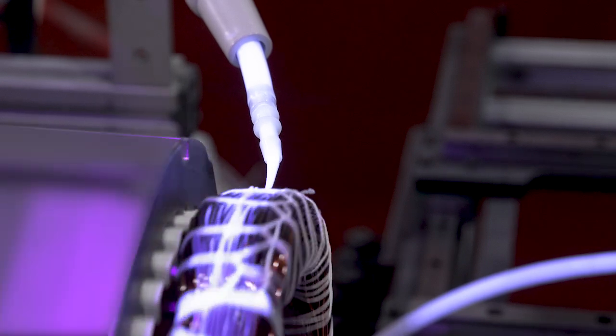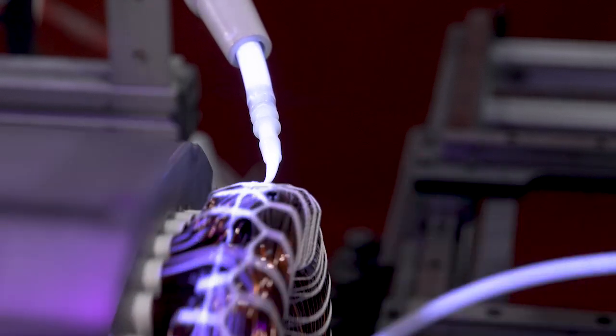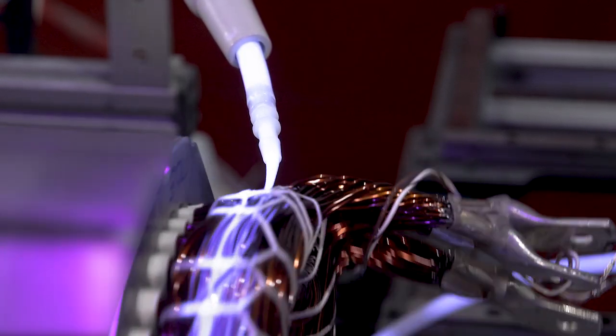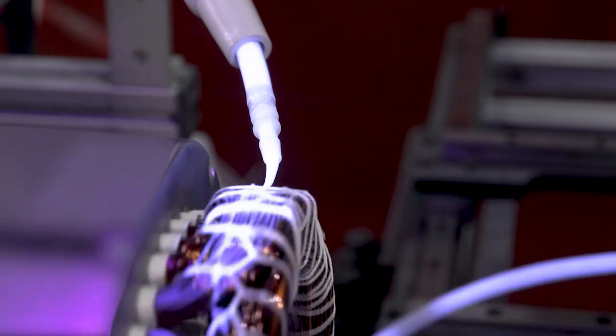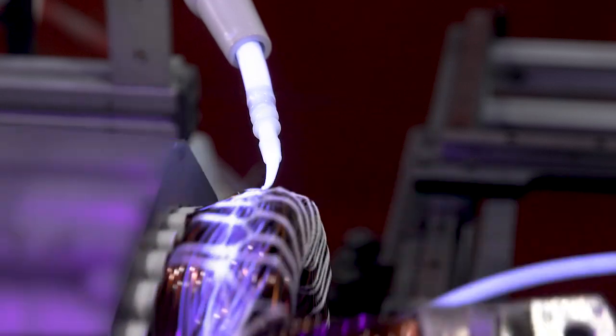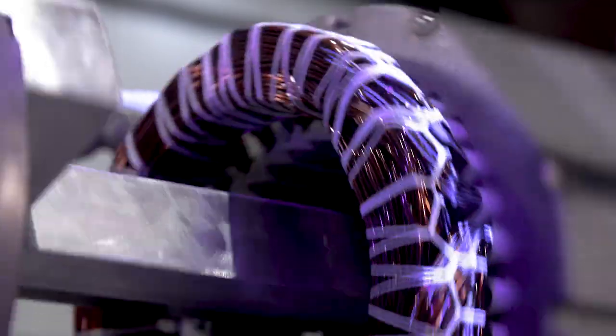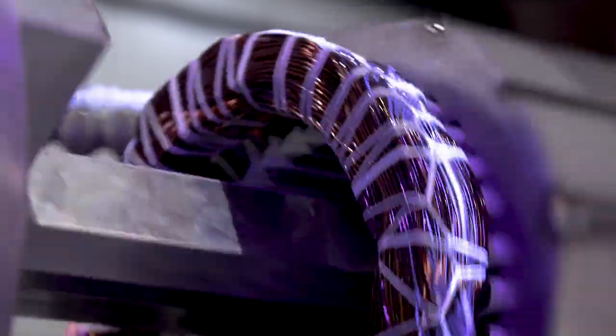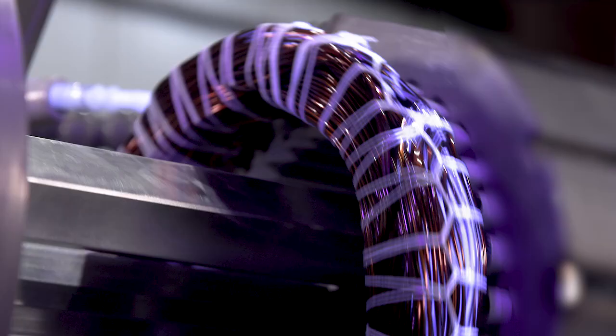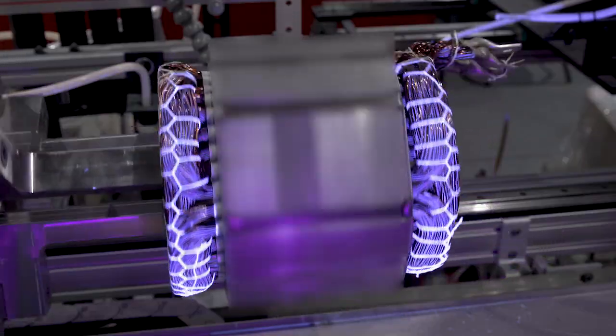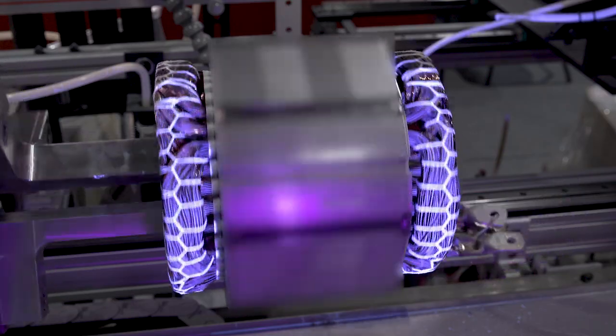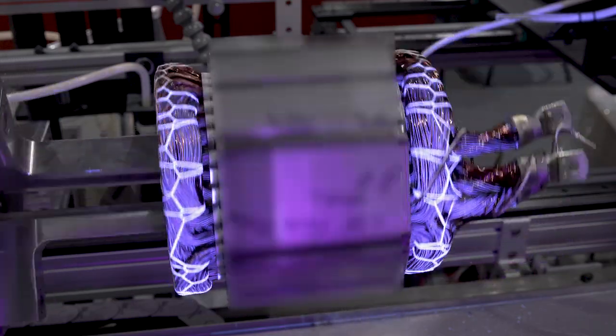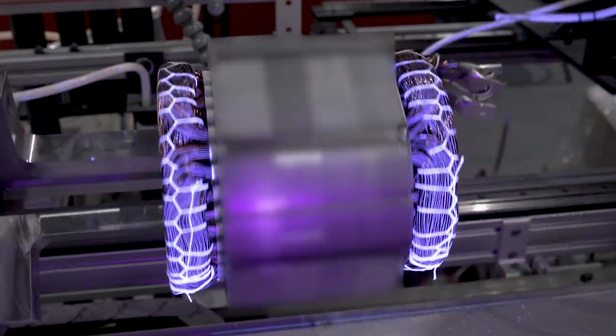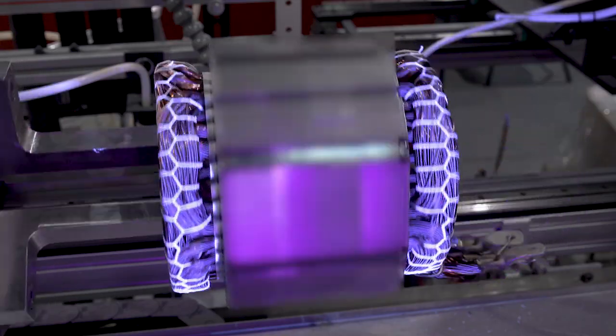With the ProPreg E240, the reactivity is such that the epoxy will body up quickly after being dispensed on the preheated stator, fully penetrating the slot area and saturating the end turns. This viscosity gain holds the resin in place and does not allow the resin to drip or move onto unwanted areas on the lamination steel through the non-heated trickle area and into the bake zone. This provides a clean, cured, finished stator that does not require additional cleaning.